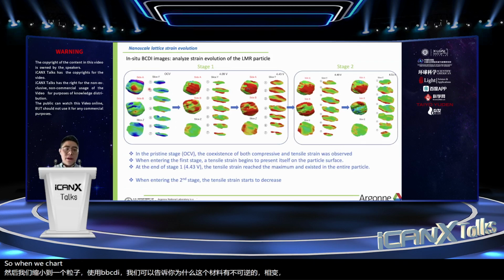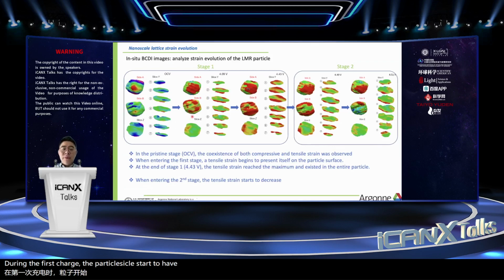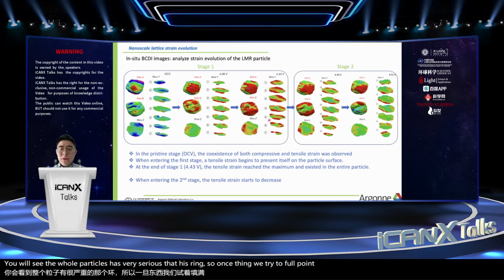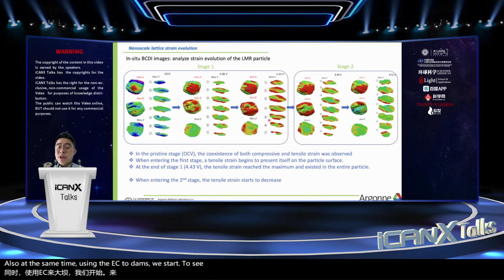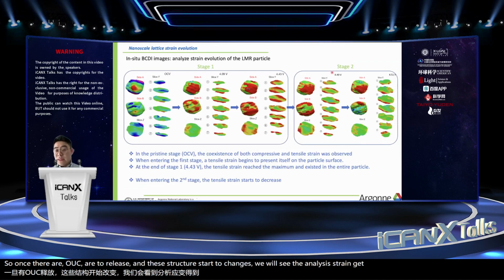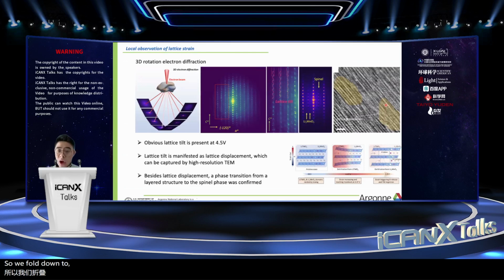So when we charge the batteries, the red and the blue mean the lattice strain. You will see during the first charge, the particles start to have some compressive strain, and then when we charge the battery to 4.43 volt, you will see the whole particle has very serious lattice strain. So once we charge to 4.43, we will start to see the second phase. And also at the same time, using the in situ DEMS, we start to see the oxygen release. So clearly, the oxygen lattice strain will trigger the irreversible phase transition, and also will trigger the oxygen release. So once the oxygen starts to release and the structure starts to change, we will see the lattice strain get released here.